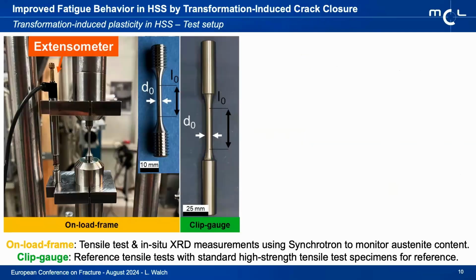The first test regime, tensile tests, for which we used two test setups, one at the German Electron Synchrotron Institute, DESY in Hamburg, and one at our local laboratory, because the setup that we had available at DESY wasn't ideal for high-strength materials due to the threads of the specimens and also the extensometer which was mounted on the load frame, and thus the strain measurements weren't as accurate as we'd have liked.